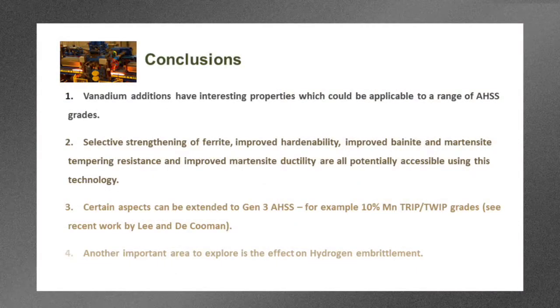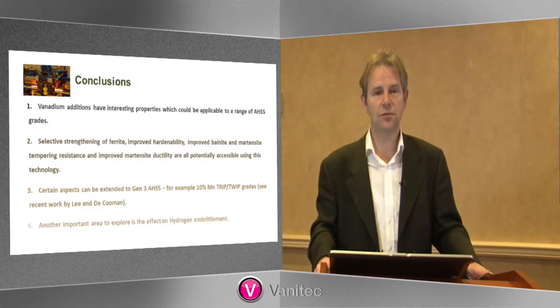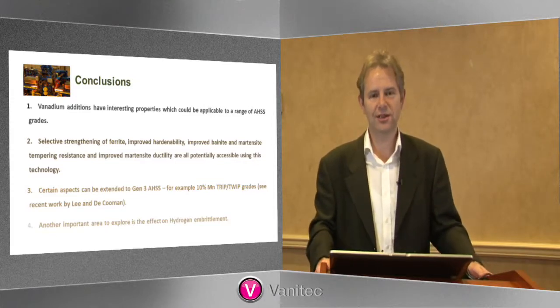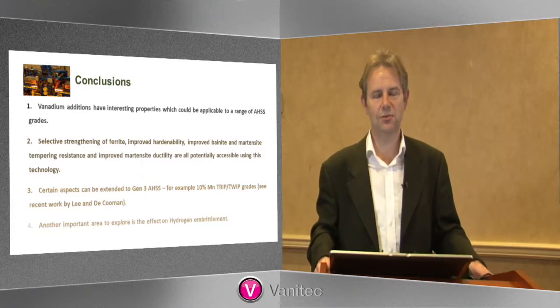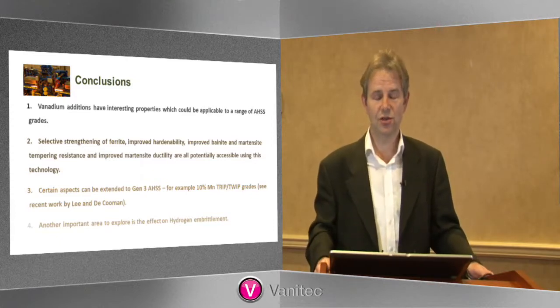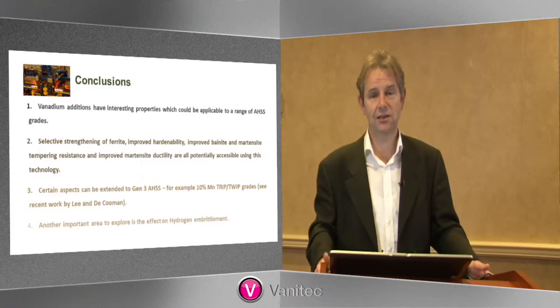Certain aspects of it can be extended to the new steels, generation 3 steels. I would take, for example, the 10% manganese TRIP grades, which have recently been shown by Lee and De Cooman. Some of those have got vanadium precipitation strengthening in them. I think there's a strong case for studying vanadium additions in high-strength steels in much more detail. There is one last area which we haven't even looked at: there is a strong interaction between vanadium precipitates and hydrogen embrittlement, which can be a big problem in these steels. So that is a completely different subject which would merit a talk on its own.